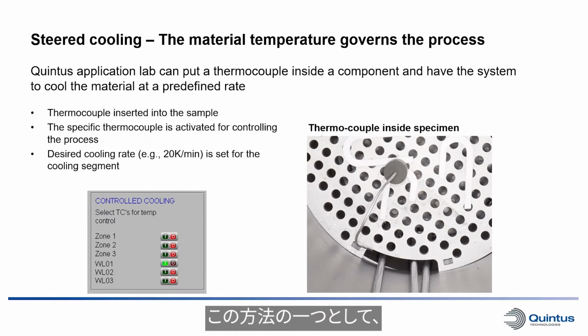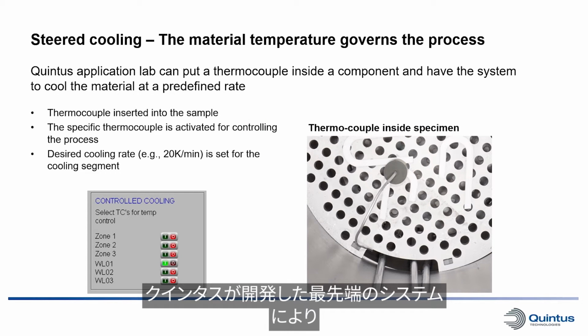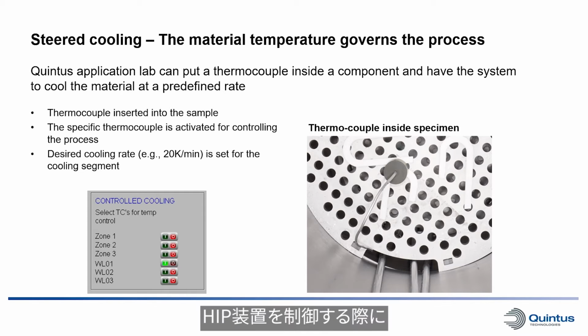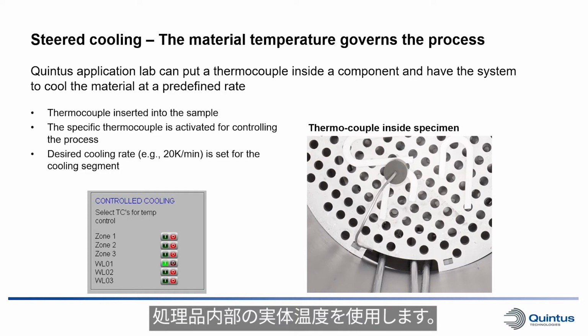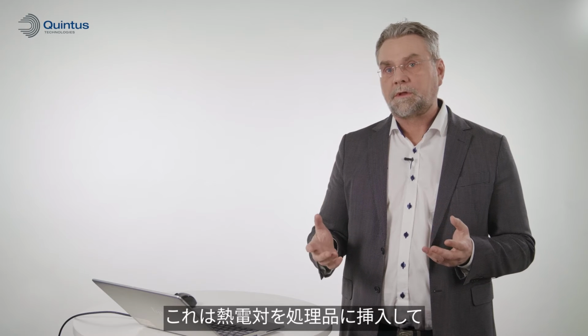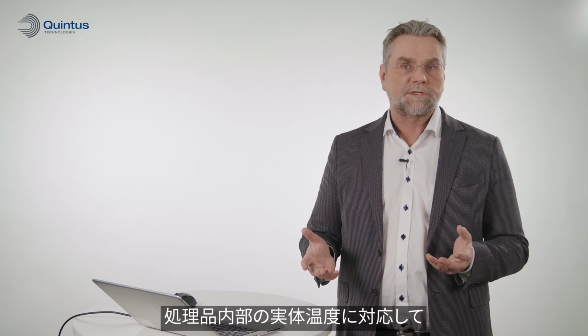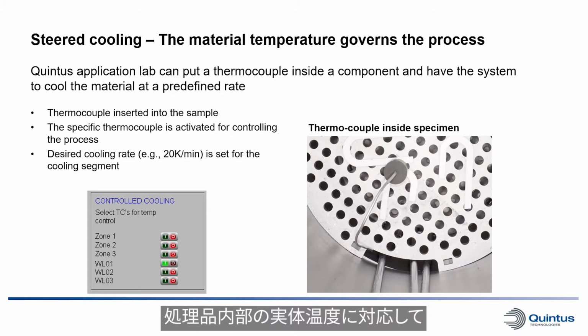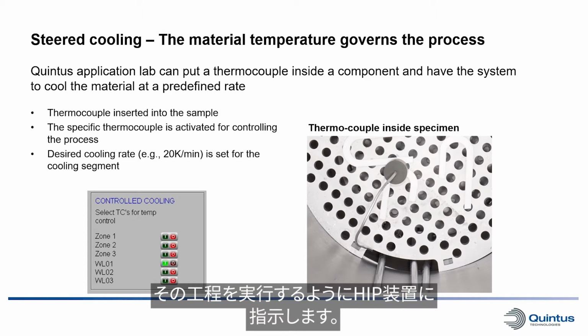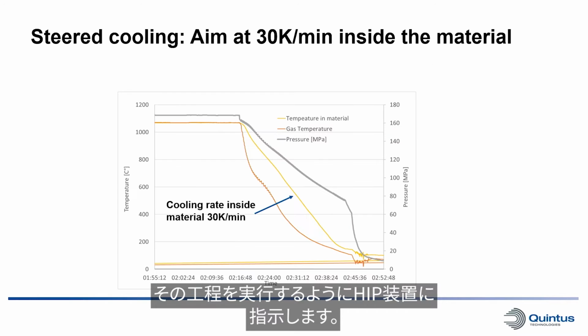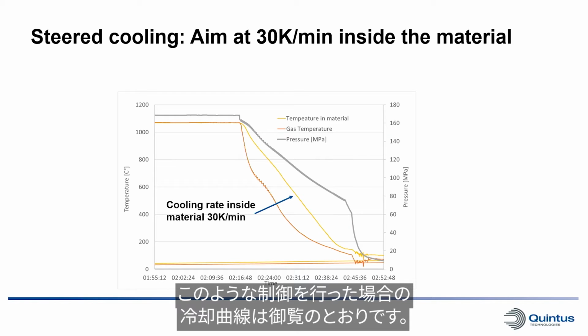One way of doing this is, of course, using the state-of-the-art system that Quintus has developed when it comes to controlling the HIP system from the actual temperature inside the component itself. And this is done by inserting a thermocouple into the component and telling the HIP system to run the segments according to the temperature inside the component.